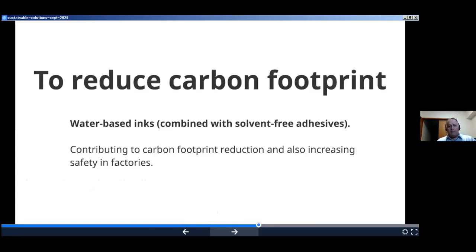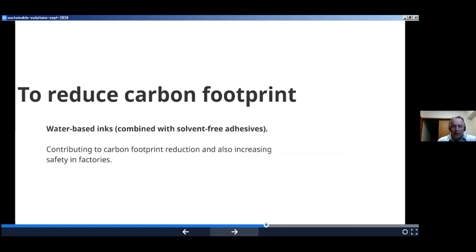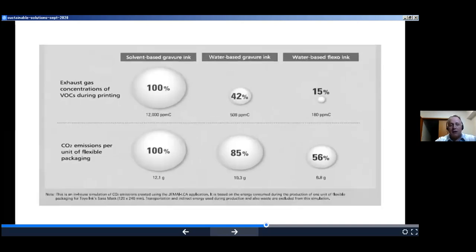So another way to reduce the emissions to the atmosphere is to reduce the carbon footprint, to reduce the CO2 emissions during the production of the inks and also during the printing process. In this case, we are suggesting customers change, for example, the printing process from solvent-based gravure ink into water-based Flexo inks. As you can see here in this graph, if we change from solvent-based gravure ink into water-based Flexo inks, the VOC emissions can be reduced by 85%, and also the CO2 emissions can be reduced by 44%. So it's quite a big change.